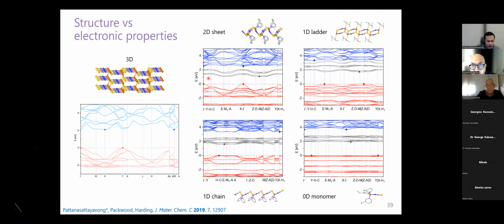And another interesting thing is also the interactions between the ligands themselves. So the gray lines here are the states formed by the ligands. In the 2D structures, some of them can have strong pi-pi interactions actually. And maybe it is possible to also have some sort of electron transport through the organic states. So then we can have hole transport through the copper and sulfur network, and the electron transport through the interactions among the aromatic rings within the 2D sheets of copper thiocyanate